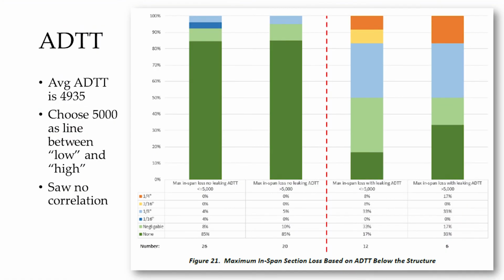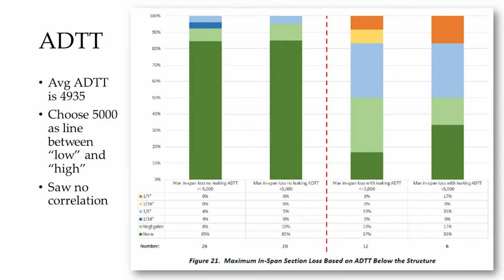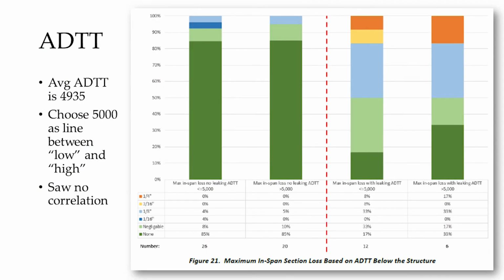Looking at traffic, they said, well, does traffic make a difference? They split the population in half, found that about half were over 5,000, half were under. So they said, all right, high volume would be over 5,000 trucks a day, and under would be less than 5,000. So once again, on this left side, your left, no leaking and not a significant difference on the traffic, which is very interesting considering Maryland and Virginia's experience.